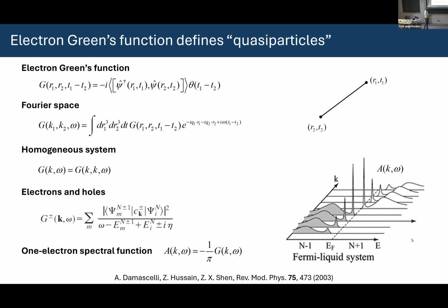So this is energy, that's the Fermi energy there. And then as a function of K, if you have some band passing through the Fermi energy, you'll typically see a resonance. The width of the resonance will go like E squared, where E is the distance from the Fermi energy. So the lifetime will diverge as you approach the Fermi energy. And then it'll have some shake-off processes that are related to whatever the collective modes are in the system, phonons or plasmons or whatever. So this is normally when people plot band structures in solids using photoemission, which I'm going to talk about in a minute.